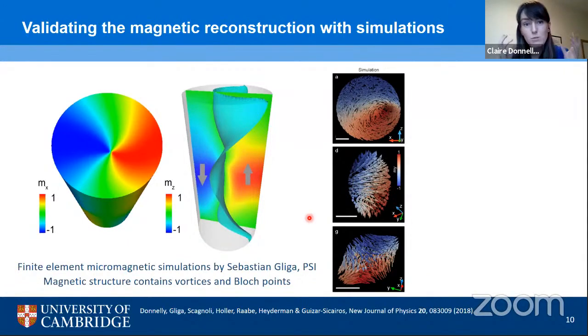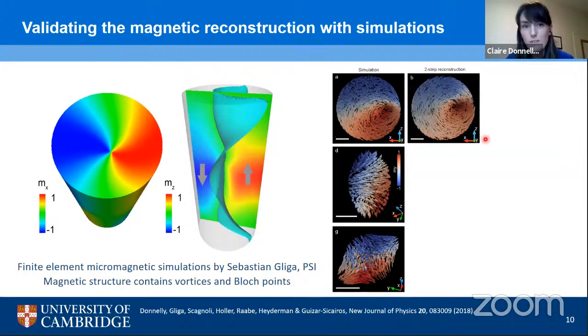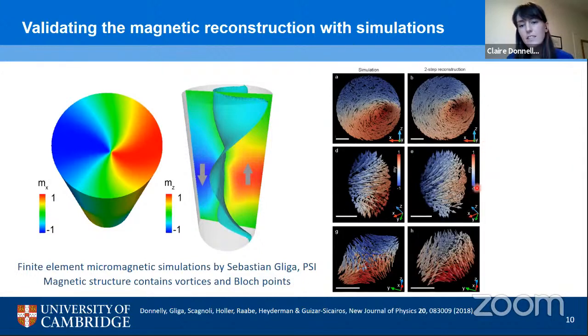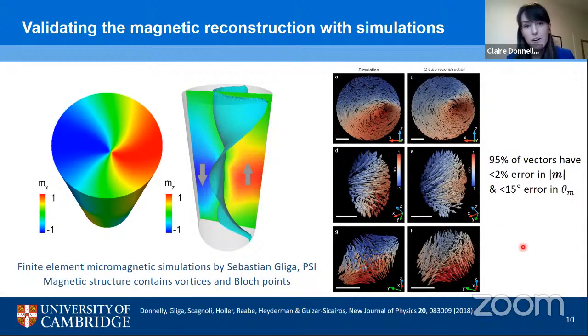And essentially what we did was we simulated the projections of this micromagnetic state for many different sample orientations. We fed this into our reconstruction algorithm, and we could directly compare our magnetic reconstruction with the original structure. In this way, we saw a very good agreement between our reconstruction of these different structures, and in general a very accurate overall magnetic reconstruction, giving us added confidence that we could really believe these exciting results.